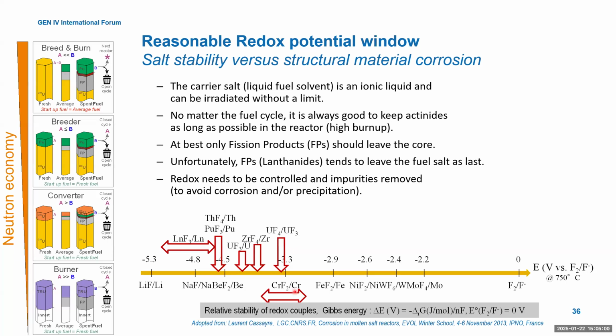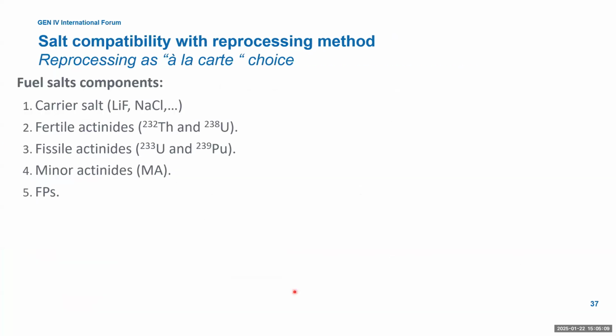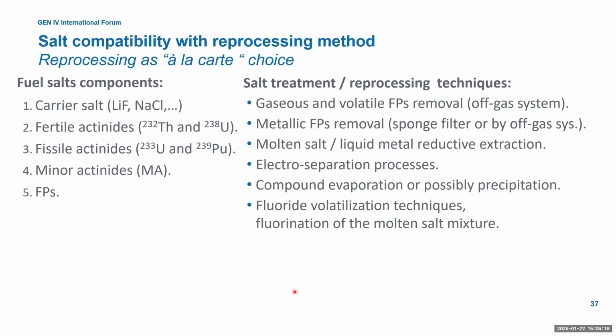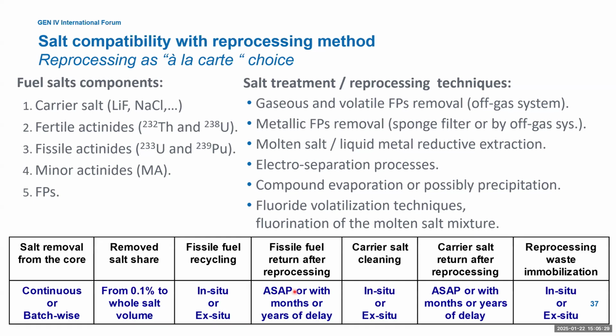So there is a temperature window, there is a redox potential window, but you should also consider the fuel cycle type and combine them all together because they should fit. So from that perspective, the salt has 5 components, and it is typically only the last, the fifth component, the fission products, which you need to remove. And for that, you can use several different methods. Sometimes you need to use several different methods to get to the fission products and to remove them. And you can apply these methods in many different modes. So altogether, it provides many different variations.